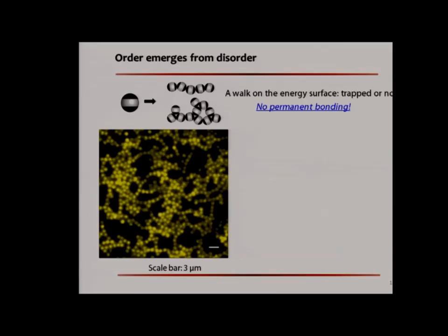So here comes the trick. It all depends on the attraction strengths between the attractive patches. They need to be strong enough to bias the self-assembly towards the structure of the lowest enthalpy. At the same time, they need to be weak enough to allow self-correction of misaligned bonds.